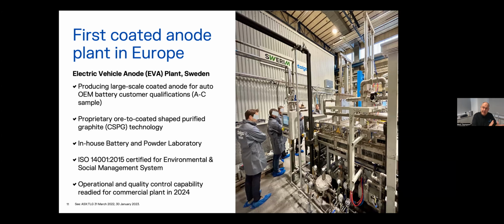The difference between anodes and things like lithium and cathode materials is that they're all chemical based on metal. So as long as you produce something to a spec metal, then people will buy it off you. The difference with anodes, and why it takes longer than people think, is the anode has to be tried because it's not just about purity, it's also about the internal crystallinity, and the way the shape of the product works. So they have to physically test it.